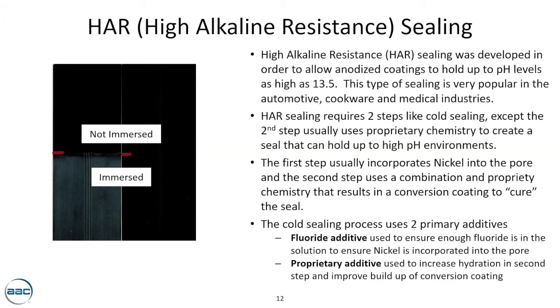What you'll see here in the image to the left is a part that has been half immersed, dyed black, into a 13.5 pH solution. The part on the left did not have the correct fluoride additive or the proprietary additive in the second step. As a result, you saw some significant color loss on the black dyed part. The part on the right had the correct amount of fluoride additive in the component and also had the correct proprietary additive in the second step. And you'll see there's no visual difference in those panels.